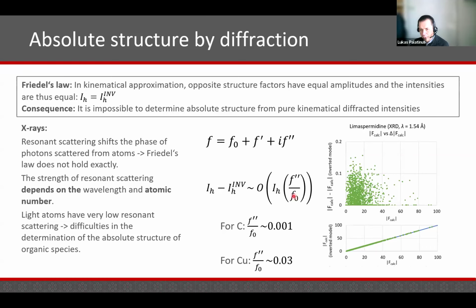Here are a few numbers. The breaking depends on the phase shift induced during the scattering process, and that phase shift depends on the wavelength and on atomic number. For small atoms like carbon, so light atoms, this effect is of the order of a fraction of a percent. As a result, the diffraction from one structure and the inverted structure is almost the same, as we can see here on this plot of F-calc from one enantiomorph and the other enantiomorph. You see there is almost a perfect straight line, so no difference.